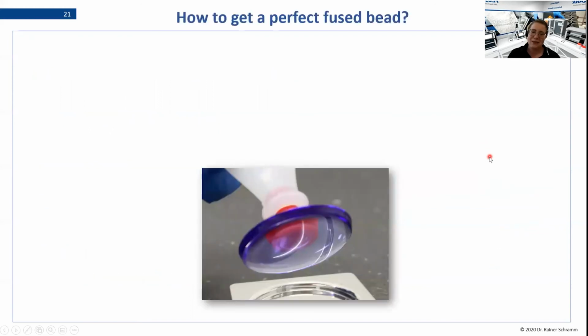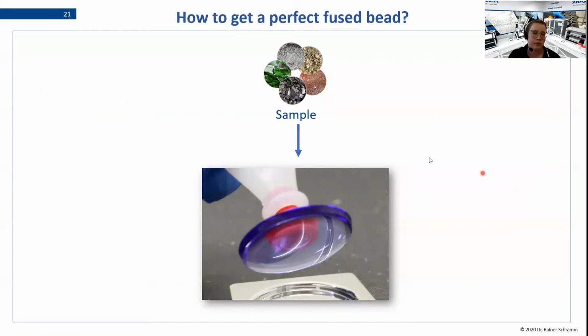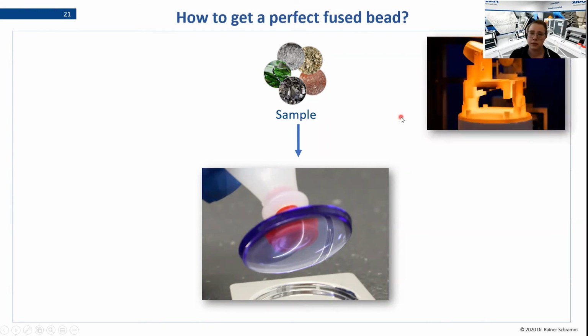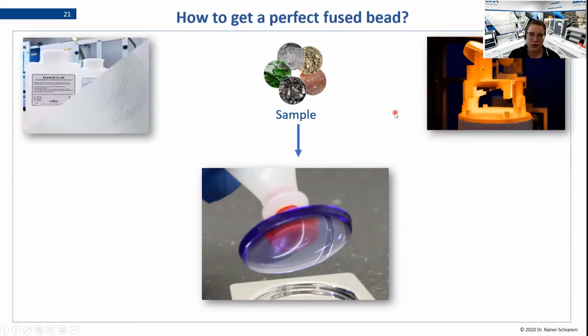So now we talked a lot about problems, but that wasn't our aim, right? We wanted to know how do we get a very nice fused bead? So first of all, we are dependent on our sample. There are samples that are not critical at all. There are samples where you don't need to think about additives or using some special flux. Then you will be totally fine and you are very lucky. But if your sample is somehow critical, there are two things you have to think about. One crucial thing is your fusion technique, and the other crucial thing is the preparation side.